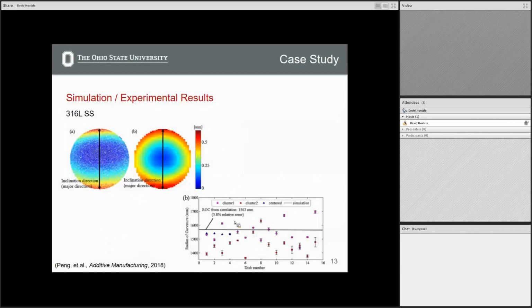This is with 316L, so it's exactly the same plot, just a different material. Our relative error was considerably lower in this material for reasons we don't exactly know why, but basically our simulations were fairly accurate in terms of understanding what the radius of curvature would be.